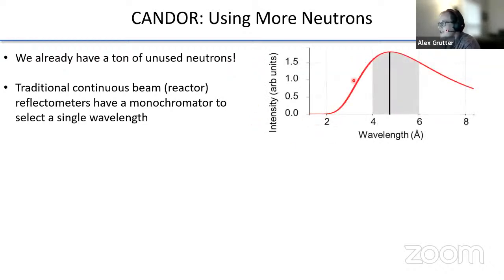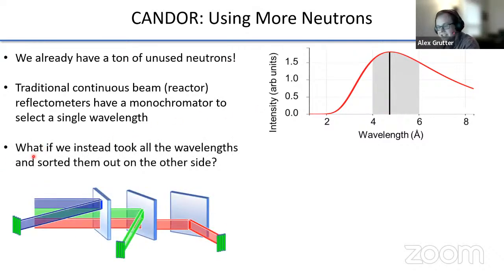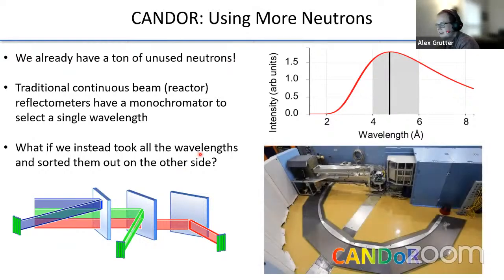But the reactor gives you a huge wide band of neutron wavelengths, and we only pick a really narrow bunch of this. But in an ideal world, we'd like to take a wider band, say from 4 to 6 angstroms. So the question is, what if we took all these broad wavelength bands, sent them all towards our sample and sorted them out on the other side with a multiplexing detector? And so that's CANDOR. That's the new neutron reflectometer, just hopefully starting soon to do user measurements at the NIST